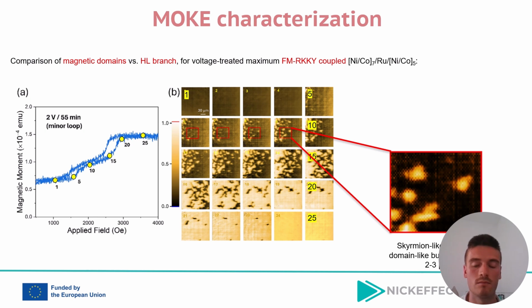with sizes between 2 and 3 microns, which are especially visible at the range of points between 10 and 15, where this nucleation of magnetic domains suggests we could even voltage control this nucleation phenomena in the case of these ferromagnetic RKKY coupled samples.